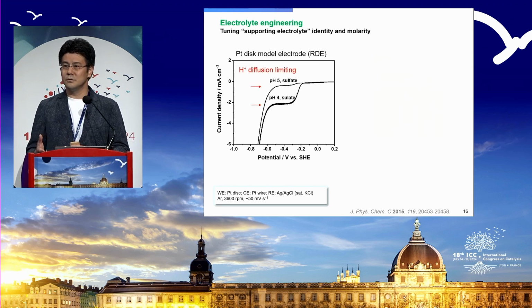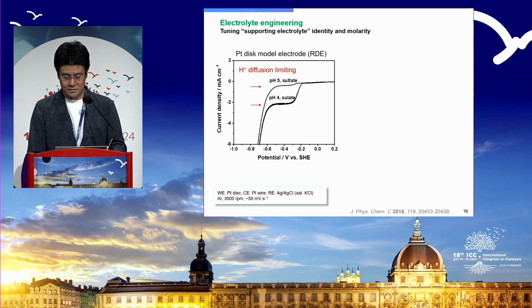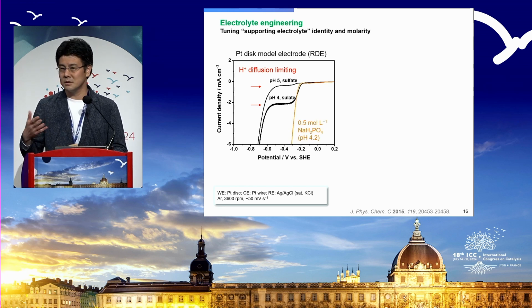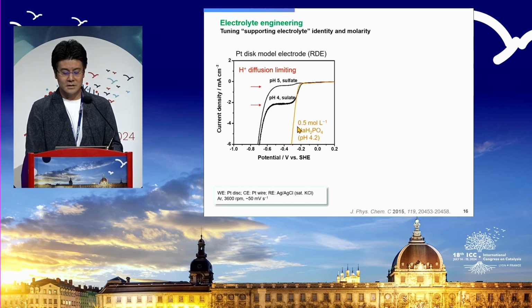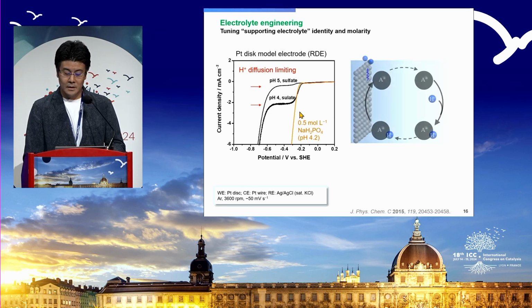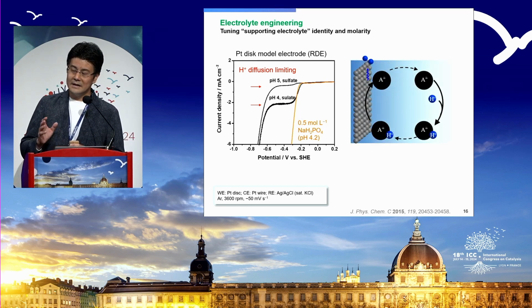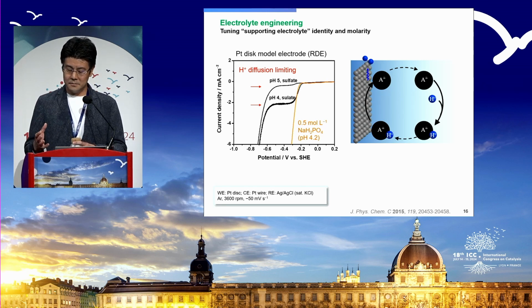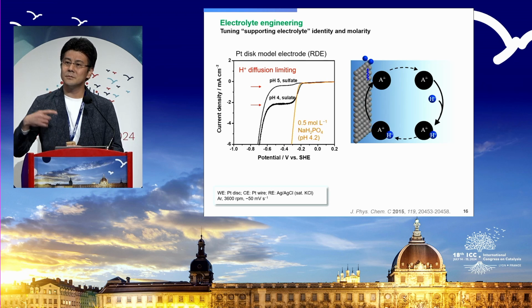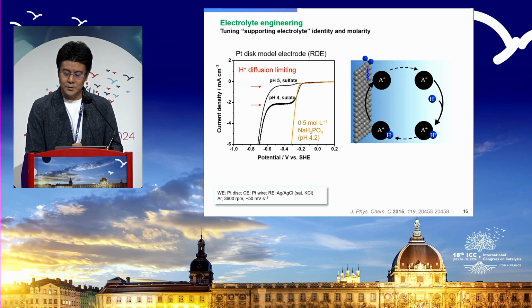So what you need to do in order to maintain the proton concentration in neutral conditions, this is again high school chemistry, you can use a buffer. The buffer can supply additional protons, so you can see that this one is increasing the current as you expected from the pH positions. But we didn't stop here. Actually, this proton is carried by the buffer anion. So anion flux has to be maximized in order to improve this hydrogen evolution activity.